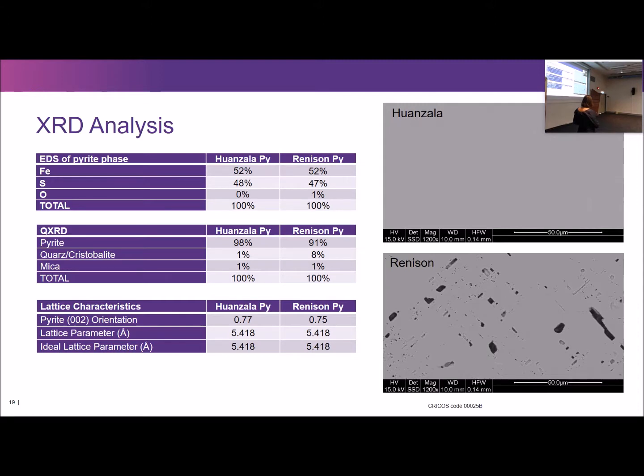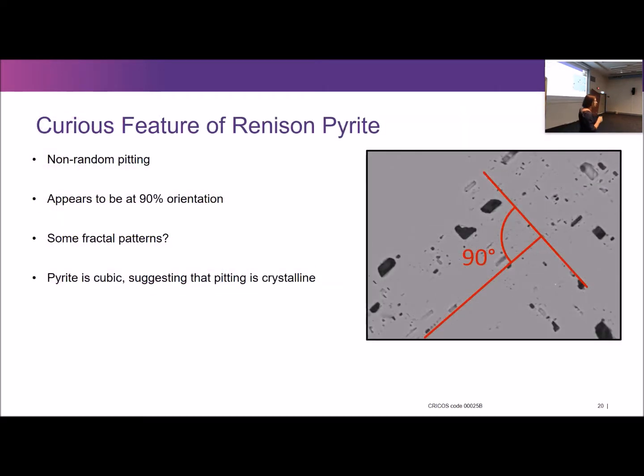And finally, I looked at the lattice characteristics, and this tells you how perfect a crystalline structure is and how much it deviates from the ideal. And they were, again, both exactly the same, and the lattice parameters matched the ideal lattice parameters for pyrite almost exactly. So, nothing. The interesting thing was the texture.